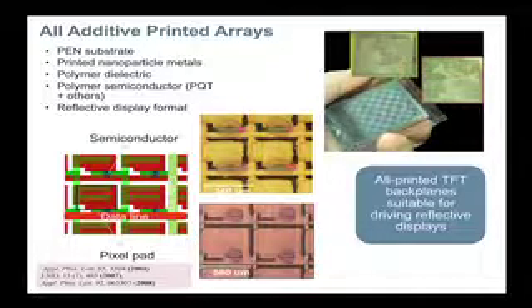So this was the file that I had in the computer. And then you say print, and this is the results that you get. So you can see here the resolution. These pixels are 340 microns. This pixel is 680 microns. Just to give you an idea, if you were to print a screen that this big, your pixel would be 1 to 1.5 millimeters square. So the resolution that you get for printing here is really good for large area displays. You don't need to go smaller. You need to go smaller for other applications.